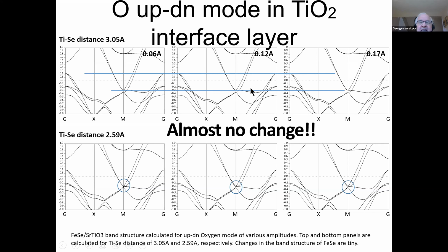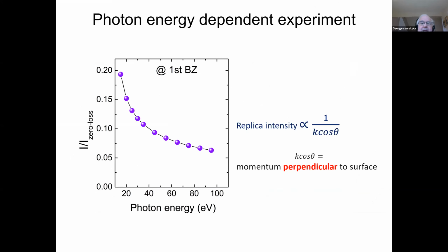And then you just look at the band structure, and you see absolutely nothing happening. So the iron d electrons really seem to be insensitive to what is happening so far away in the strontium titanate. Now, in our paper that we published about the extrinsic energy loss, we also gave the smoking gun experiment as to how to determine what it was. And that's the photon energy dependence of the replica intensity. It should go like this if it's extrinsic.